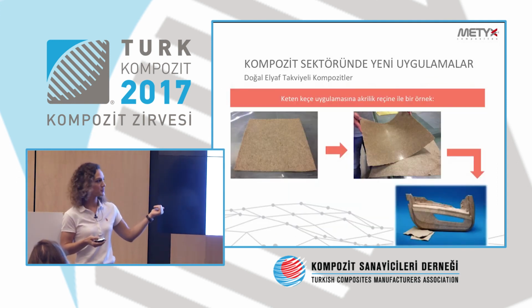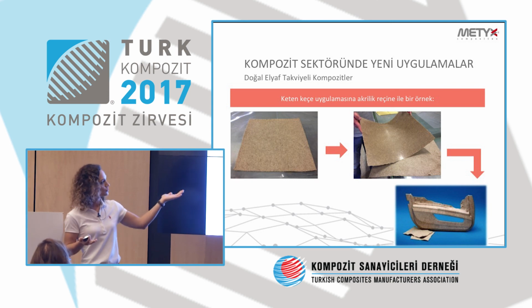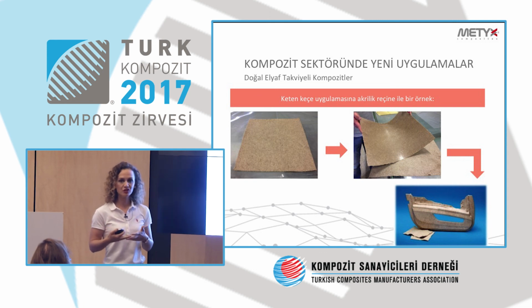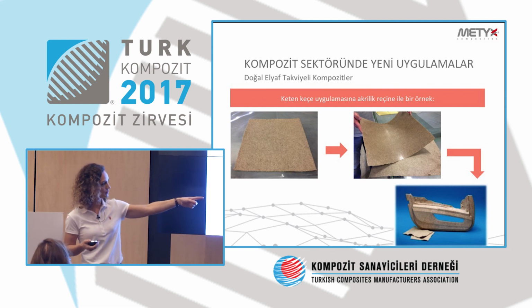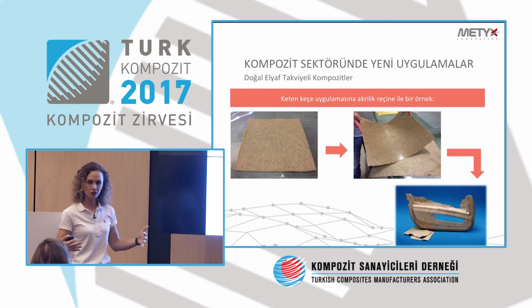For example, there is another application we have done. We have taken mat-like flax, and there is a water-based resin. We have dipped it in, and we have created a prepreg, and you shape it when it is hot. I have shown it in the previous example. Inside the door panels, for isolation reasons, it is possible to use it. And you can thicken it, and you can create furniture out of this material.